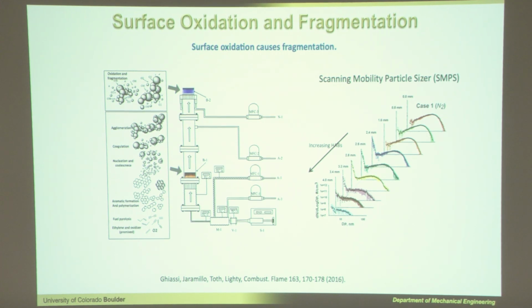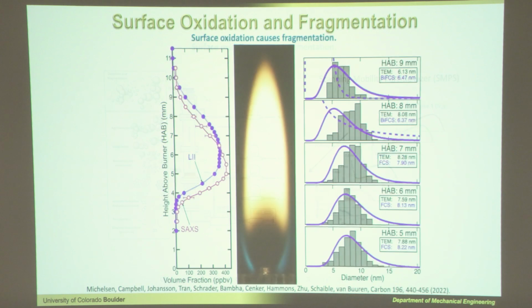And I think they can get rates from this study to figure out how fast you're getting those particles to go away. Okay, so we can see when we do SAXS measurements without sampling from the flame, we can actually look at oxidation rates. And we see something similar just by doing, so we have our X-ray probe sending it into the chamber, into our flame, and we detect the angle at which we scatter. So that allows us to get the size distribution of our particles.